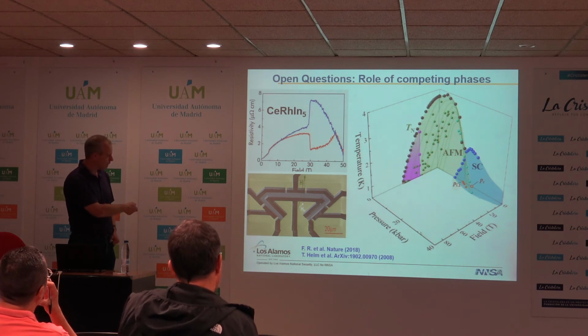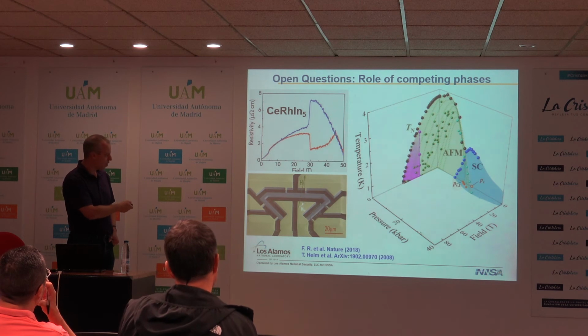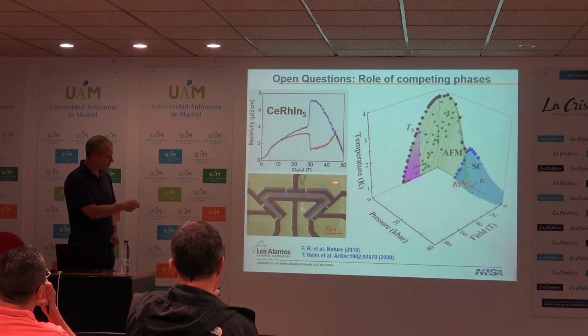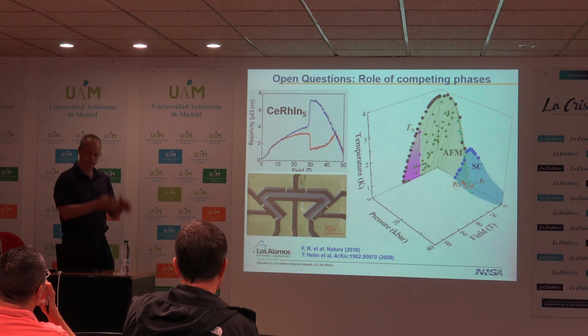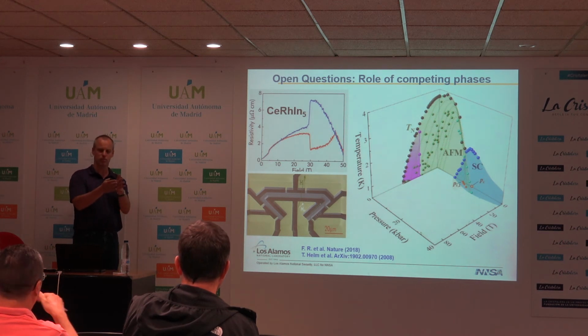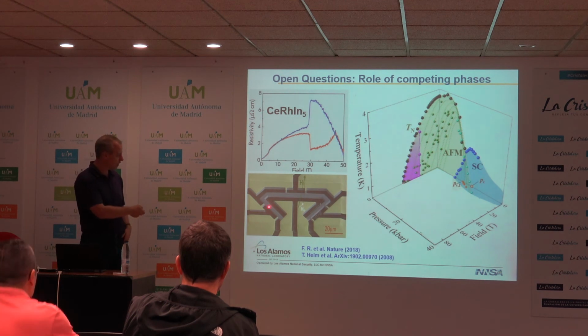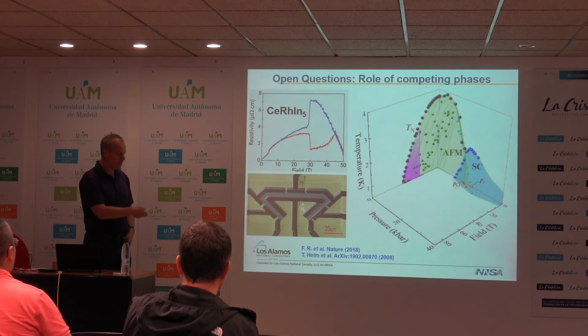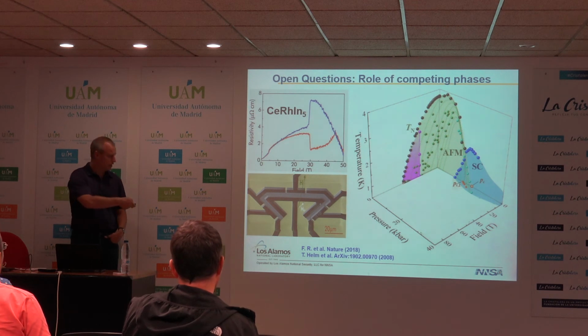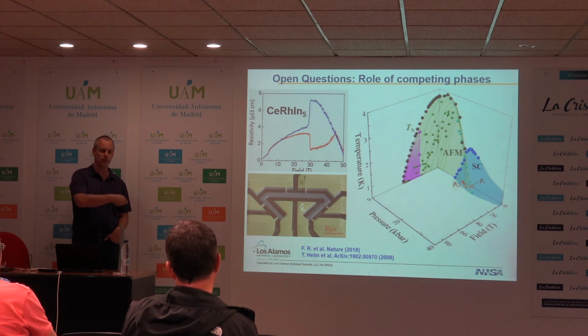And this was really enabled by some beautiful work from Philip Moll, where he used this focused ion beam milling. There's a crystal of cerium rhodium indium 5 that you can kind of see outlined here. He FIBs out this small piece, it's about just 2 microns thick, lays it down on the substrate, and then FIBs it again, so that you can actually do high field measurements. Now, this is really important because to do resistivity measurements in high fields of a highly conducting sample is incredibly difficult. So you have small signal to noise in general.